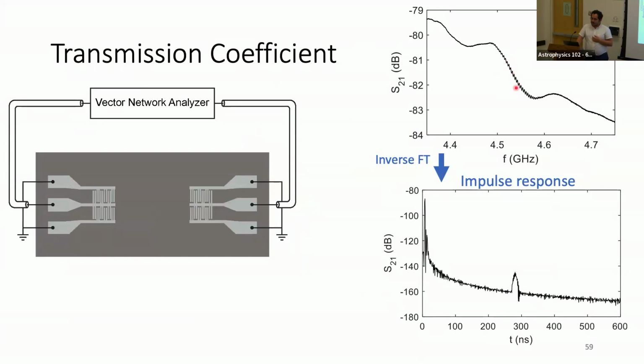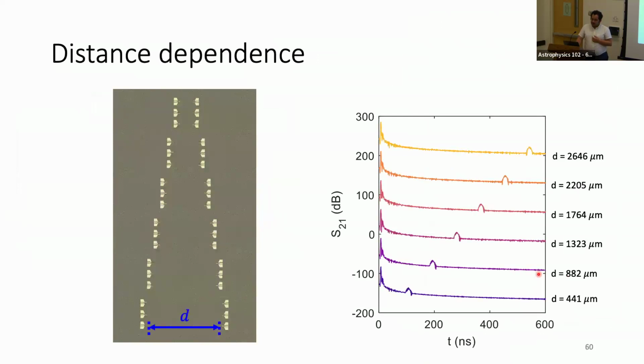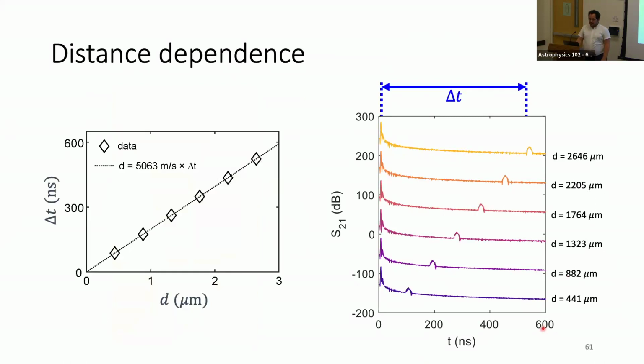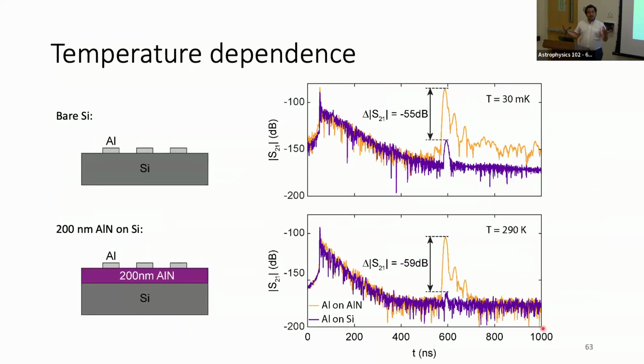In the frequency domain, you get these interference fringes, but in the time domain it's more clear. You get an impulse response due to phonon transmission at a slow propagation velocity, which corresponds to detecting a surface acoustic wave. To make sure we're not being fooled, we changed the distance between the electrodes, and we see the transduction delay scales with the distance. We can indeed measure the speed of surface waves on silicon, consistent with literature values. So it's pretty clear that we're measuring this effect: you can put metal on silicon and get piezoelectric transduction.